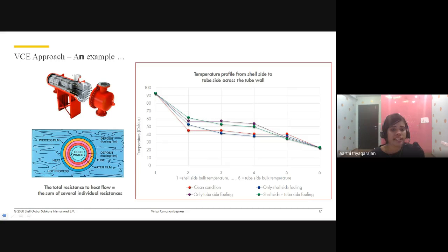So this is an example called open recirculating cooling water, the picture that you see. In each asset, there are about a few hundreds to thousands of such equipments, so-called heat exchangers. As a chemical engineer, many of you would know it better than me. A heat exchanger can in turn contain tens of thousands of tubes, the majority of which are fabricated from carbon steel. The failure of such tubes by corrosion is a common cause of unexpected plant downtime and lost production. As we know, around 60% of carbon steel tubes in cooling water service will fail well before reaching their design life. The three most likely corrosion mechanisms in these exchangers are microbially induced corrosion, in short called MIC, erosion corrosion, and under deposit corrosion.